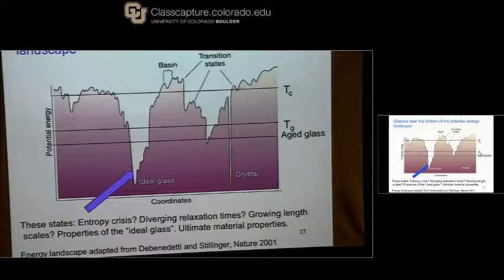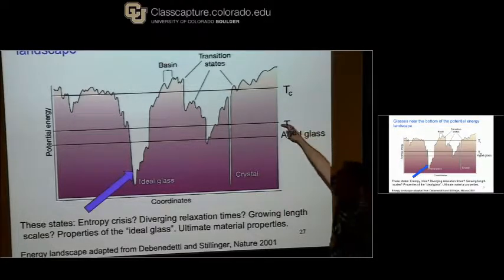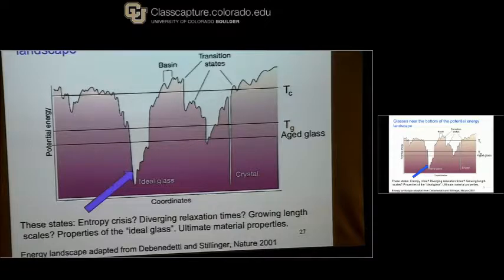For a system at equilibrium, at high temperature, our potential energy is high, and so we're experiencing what's going on at the top of the landscape. So Tc here would indicate something like the mode coupling temperature, Tc. As we cool a supercooled liquid, it stays in equilibrium for a while. The typical Tg that we would get when cooling, say, 10 degrees a minute, would be something like this point here. So now we're exploring the behavior of the basins that are found lower in the energy landscape. There are fewer of them, right? This is related to the configurational entropy going down.